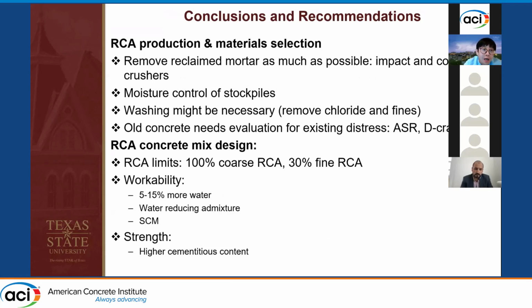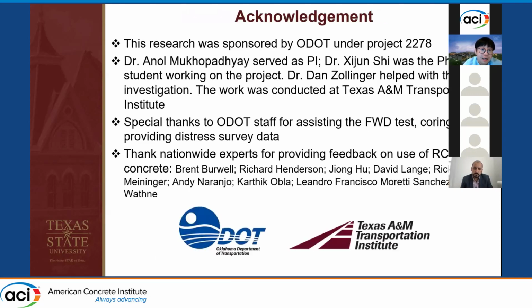So there are some conclusions. We want to remove reclaimed mortar as much as possible. We can use the impact or cone crushers. We want to control the stockpiles, and some people suggest washing aggregates may be helpful to remove contaminants and fines. And we also need to evaluate the existing distress from the old concrete. And typically we can allow 100% coarse RCA in concrete pavement. In some states like Texas, we allow 30% fine RCA. And for workability, we can use some strategies to improve the workability, and we can also use more cementitious material to improve the strength.